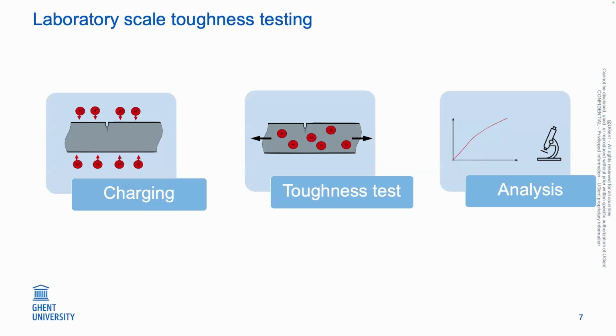Further, I will tell you a bit more about the toughness testing. First, we pre-charge our specimens. Then we do our toughness test, which is a single edge notch tensile test. And then we analyze based on the things we measure during the test. Also afterwards, we look into the microscopy and the cross sections of those specimens.